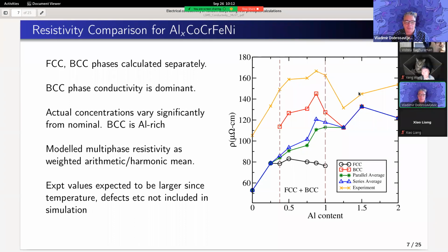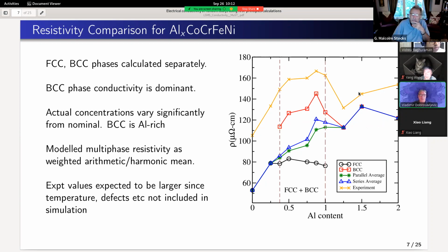And in particular, there is an effective medium approximation in percolation theory where one can actually put the resistivities of each component of the mixture and get a result. So I think it would be interesting to see if, rather than doing parallel and series, you actually did this percolation theory more consistently. Presumably you'll get something similar, because these two are very similar, but more justified perhaps, right?